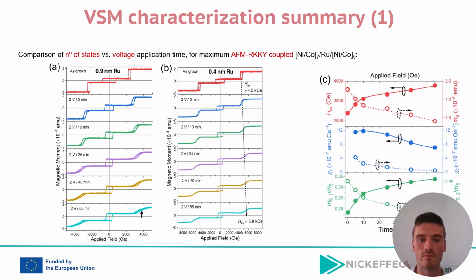Increasing voltage duration, fixing 2 volts and going from 5 to 55 minutes in subsequent time steps, gradually changes the number of magnetic states and the switching behavior, as we can well see in both panels A and B.